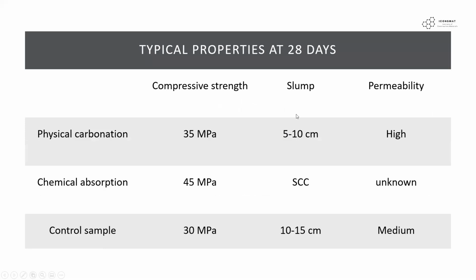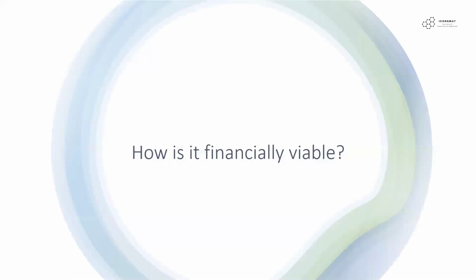Now we can compare the physical approach with the chemical treatment approach. Both aim to use CO2 gas. You can see that we achieved 45 megapascal for the compressive strength in the chemical approach. The slump flow was similar to self-compacting concrete, and the permeability test is still awaiting to be done, most probably after this COVID-19, when the universities turn back to normal.